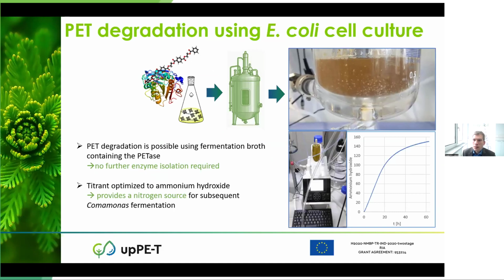In order to further optimize the PET degradation for the subsequent fermentation using Comamonas and Haloferax, we also tested whether it is possible to degrade the PET using the enzymes directly from the fermentation broth without breaking cells, without isolating any enzymes. This has got two advantages. Firstly, it saves us a lot of work to isolate the enzymes, and furthermore, the nutrients which come from the E. coli cultivation medium can also be used for cultivating the Comamonas and Haloferax in the end, which means that we are not wasting any material here, and we optimize the carbon efficiency.